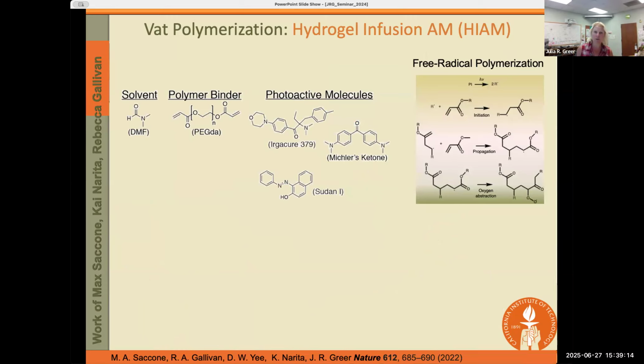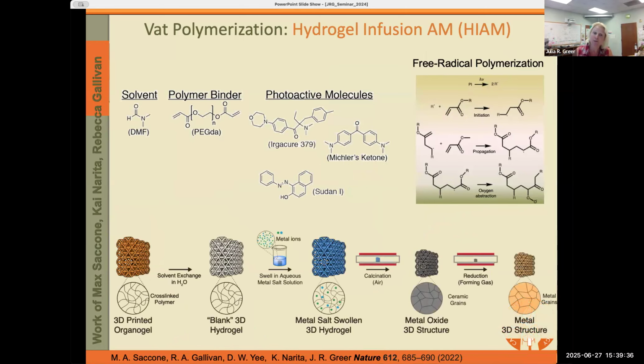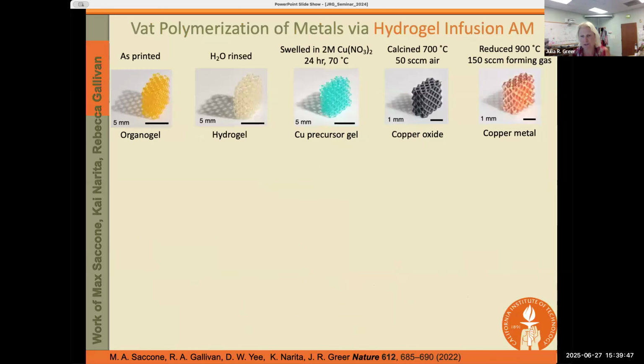I would now like to move on to introduce a particular additive manufacturing strategy that we coined hydrogel infusion additive manufacturing. And I already gave a little bit of a hint to it when I showed you how we made the oxides. So the idea here is that if you have the right cocktail of photosensitive, photoactive molecules, and then you infuse the metal salts into it, you can get this hydrogel that's swollen with the metal ions and then subjected to thermal treatment, which will ultimately give you the metal oxide and eventually the parent metal. So what we're showing you here is the work done by my former student, Max Saccone.